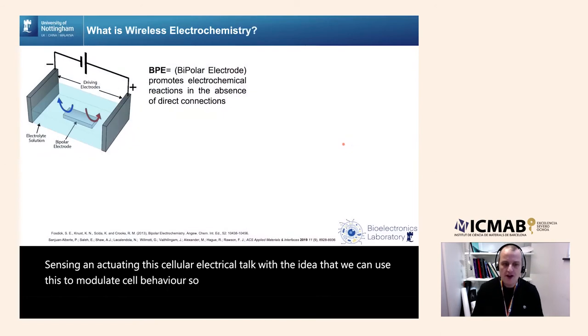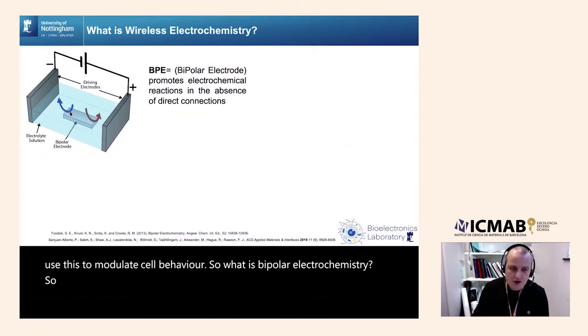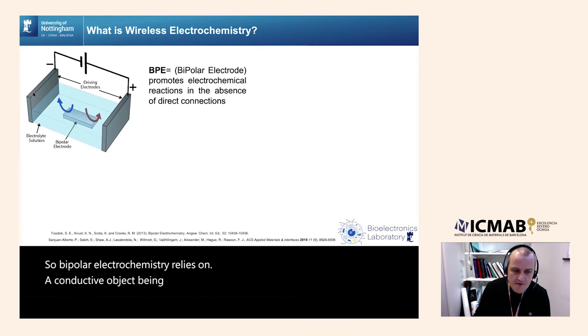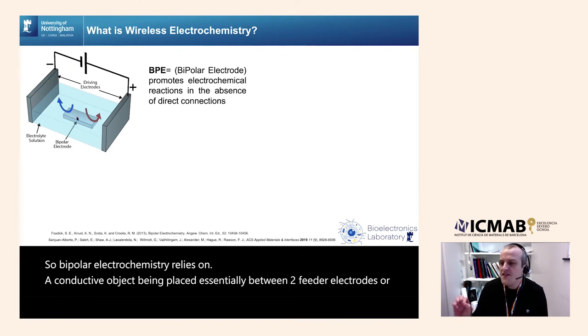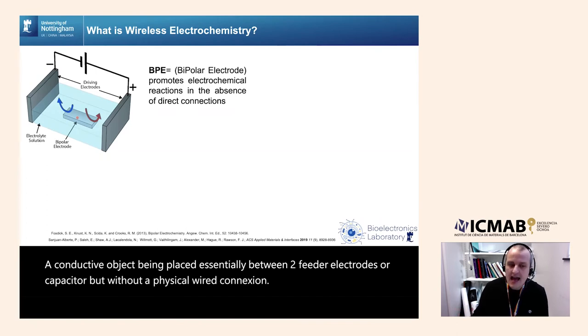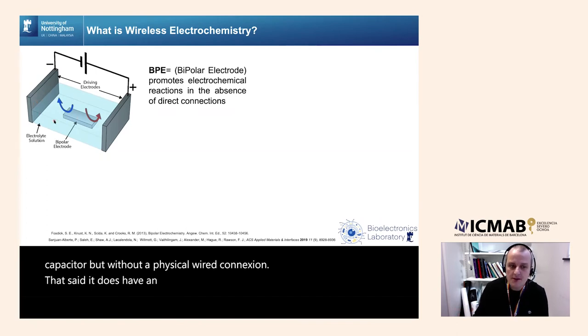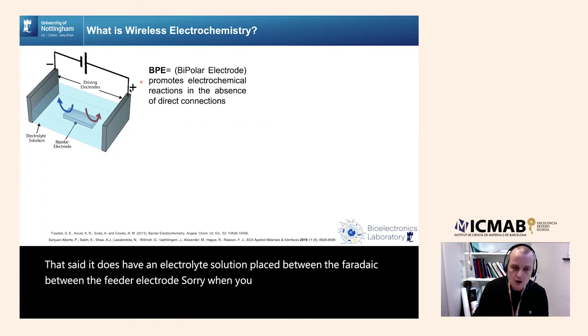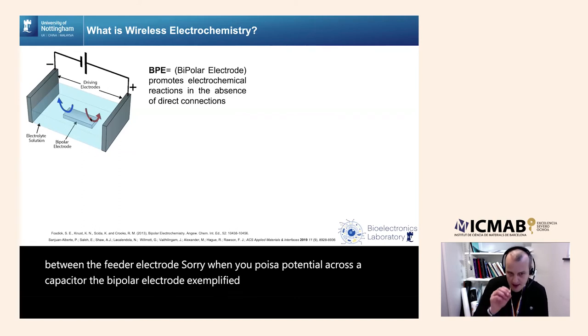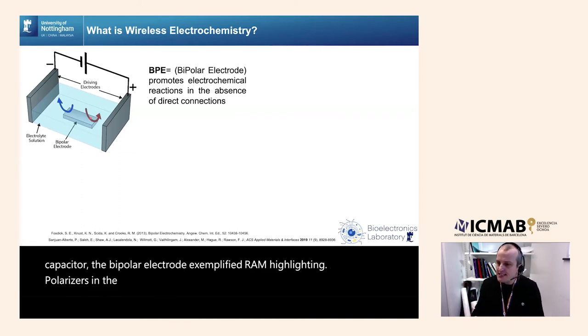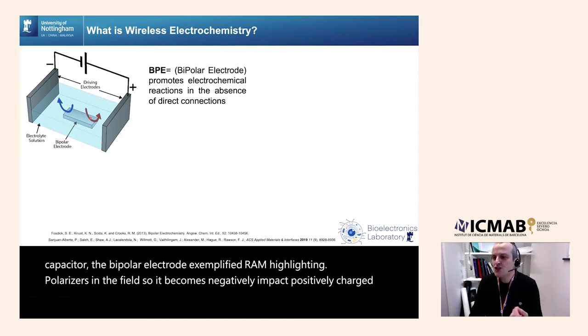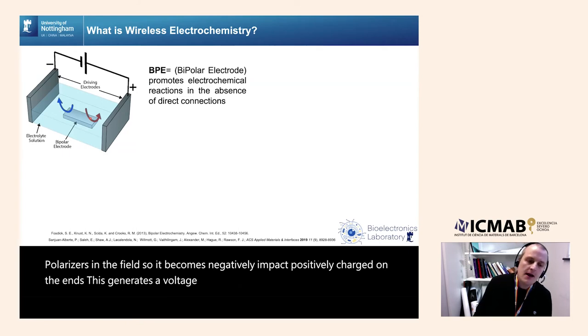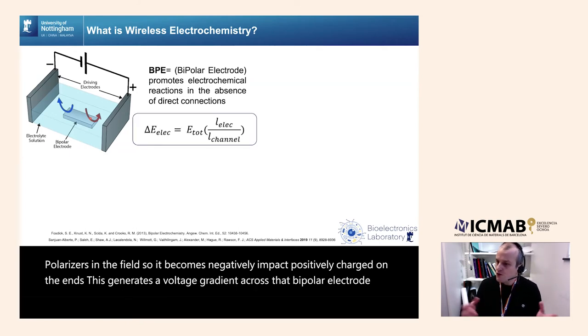So what is bipolar electrochemistry? Bipolar electrochemistry relies on a conductive object being placed essentially between two feeder electrodes, a capacitor, but without a physical wired connection. That said, it does have an electrolyte solution placed between the feeder electrodes. When you poise a potential across a capacitor, the bipolar electrode, exemplified where I'm highlighting, polarizes in the field. So it becomes negatively and positively charged on the ends. This generates a voltage gradient across that bipolar electrode, which we can use to drive faradaic reactions.